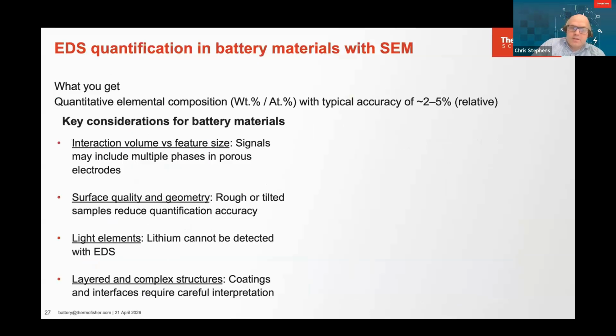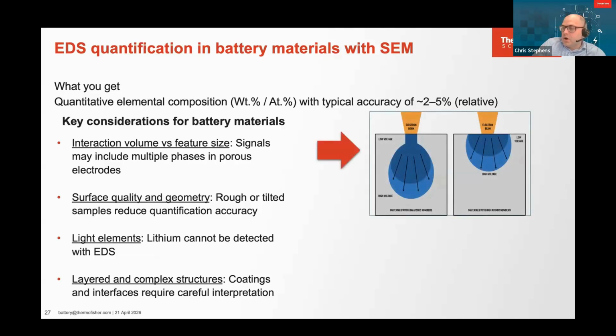So here I want to tie this through to some of the sample preparation itself. As I mentioned, you'll get quantitative elemental composition, and depending on that sample preparation, you get maybe 2 to 5% relative accuracy. But there are various things that you're going to want to consider, right? What I'm saying with this is the composition itself will really depend quite a lot on how the sample itself is prepared. As the beam interacts with the surface, you get these interaction volumes, and ideally the sample would be homogeneous within that region.